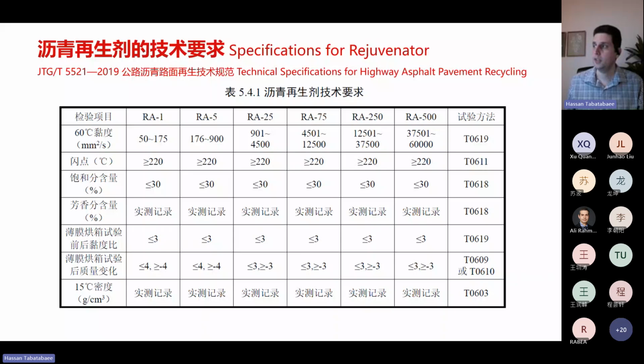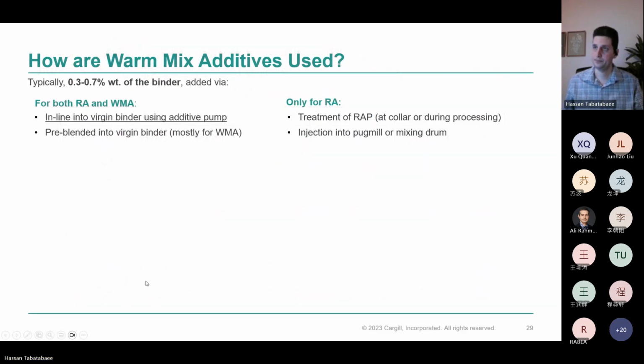There's a pretty similar table, as you can see here. This table, from the specification of the highway asphalt pavement recycling requirements in China, has similar requirements to the ASTM table. However, it does not have the 2020 update that occurred in the ASTM table, the addition of the RA0 category for the lower viscosity, which would allow the use of those bio-based additives with this specification without changing any of the physical chemical requirements that are here.